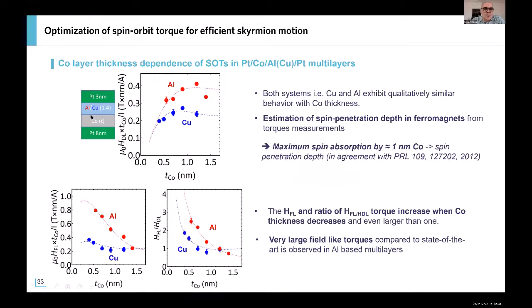Here is a summary of the results. You see these two systems, platinum cobalt aluminum, or platinum cobalt copper, the damping-like torque as a function of the cobalt thickness. You see clearly that first you reach a maximum for the damping-like torque, associated with the optimum thickness of the magnetic layer in order to absorb the spin current that is mostly generated by the spin Hall effect in the platinum layer. But interestingly, there is a big difference between the two systems with two different light elements. And this is not only on the damping-like torque. For the field-like torque, you see a large increase in the case of aluminum, which is associated, I will not enter into the detail, with the fact that with the aluminum you have a strong contribution that can come from the Rashba state and the torque associated, the field-like torque, at the interface with cobalt.